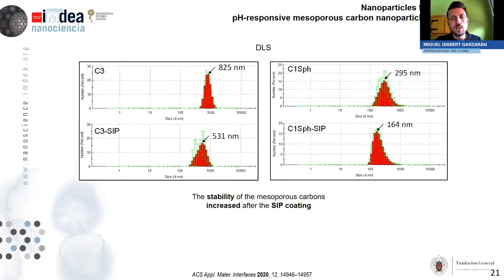And this is also very interesting because carbon nanoparticles are very hydrophobic, meaning that it is nearly impossible to disperse them in water. So it was very difficult for us to carry out the dynamic light scattering experiments, or in other words, the colloidal stability in water. But after functionalizing the nanoparticles with the SIP coating, it was much easier, and we obtained much better results. So we can conclude that the SIP coating improved the colloidal properties of our nanoparticles.